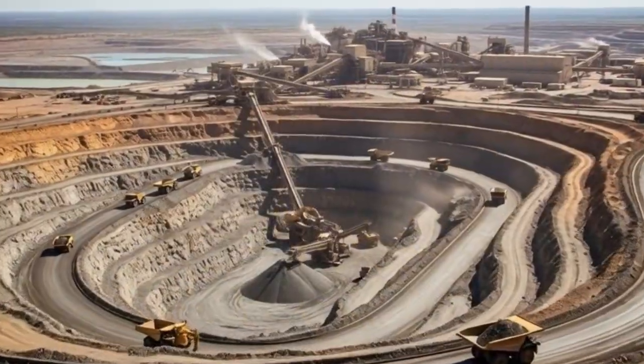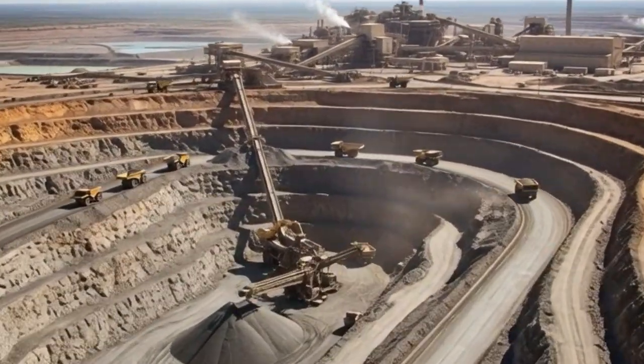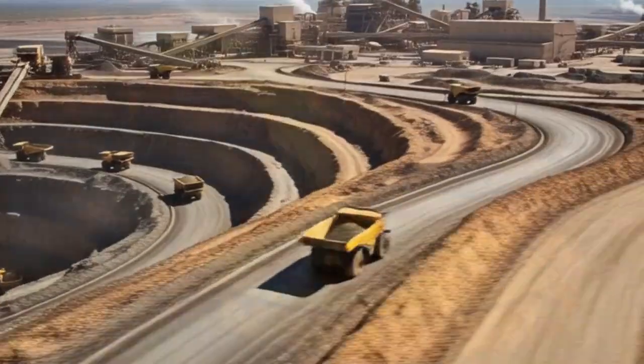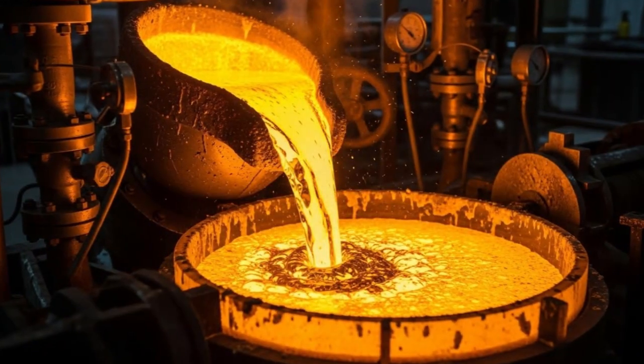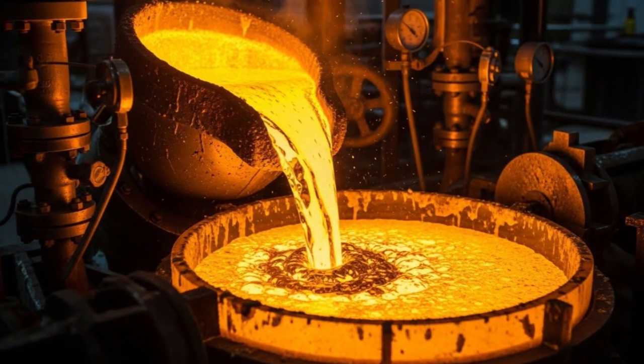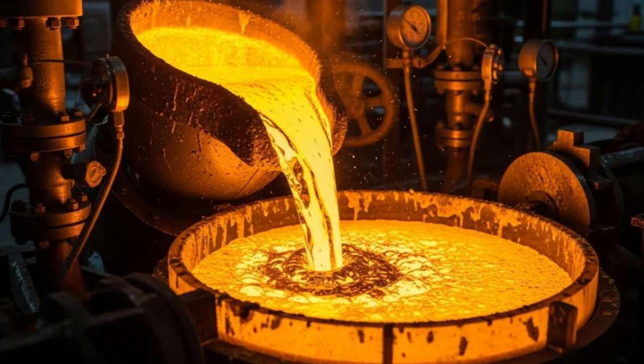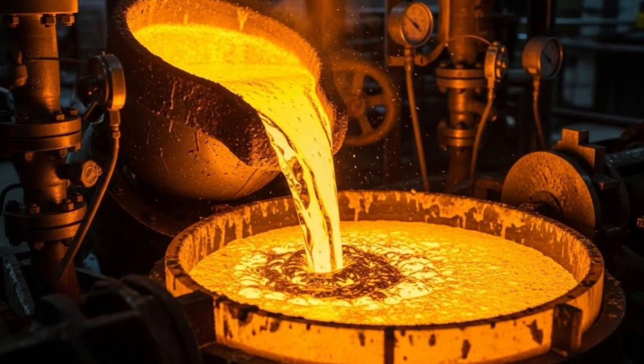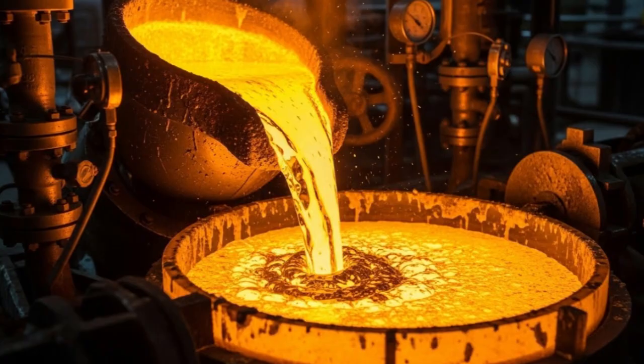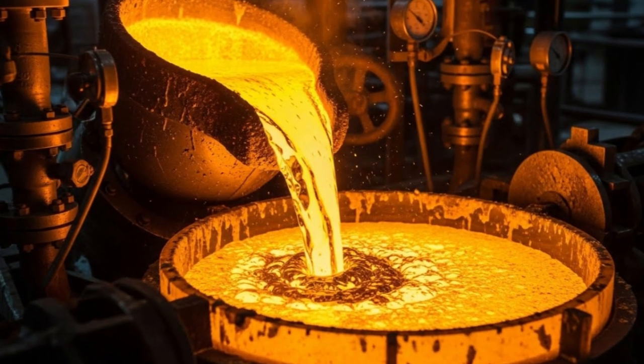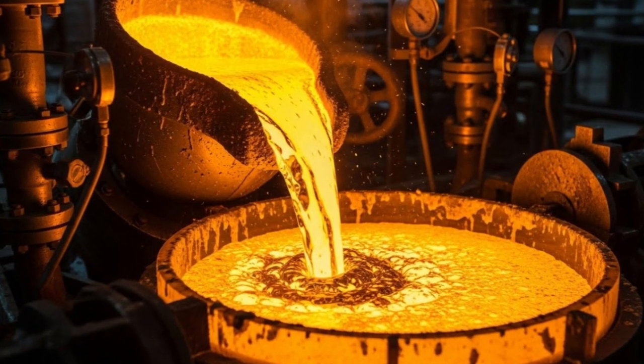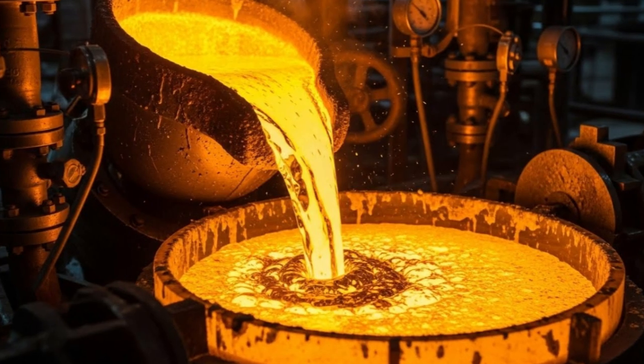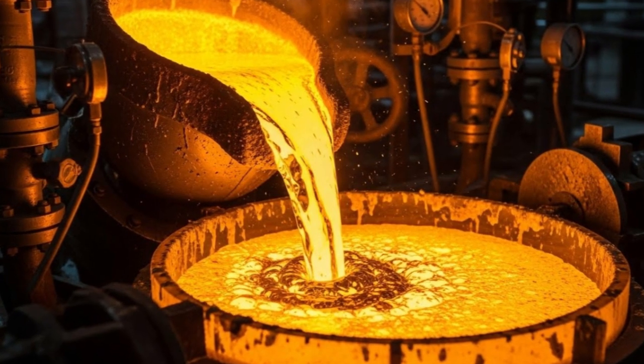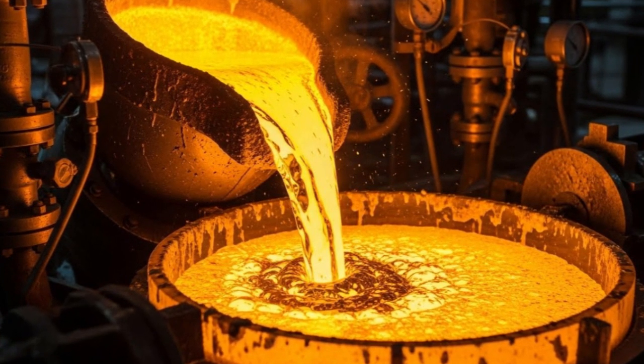Cyanide has a unique ability. It bonds strongly with gold while leaving most other minerals untouched. Under tightly controlled conditions, a dilute cyanide solution is introduced, oxygen is added to accelerate the reaction, and gold particles chemically dissolve into the liquid. As this happens, the gold transitions from a solid metal into a dissolved state, becoming completely invisible within the solution.